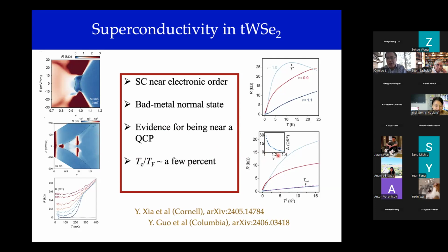And one sees that this A coefficient is increasing by more than an order of magnitude. And so that provides evidence that the effective mass, m star over m, is increasing, the system is becoming soft, and very much like the phenomenology of many heavy fermion superconductors. The direct evidence for things like T-linear resistivity, etc., for strange metal behavior is not actually that strong at all. But nonetheless, it suggests that in the part of the parameter space that has not been reached, there's in fact a quantum critical point, and superconductivity is happening not too far away from the quantum critical point. At least it allows that hypothesis.